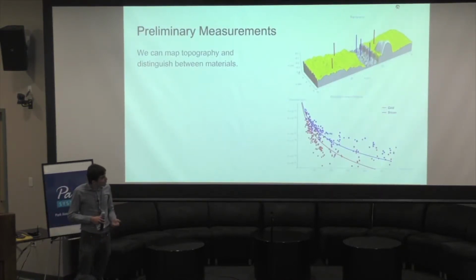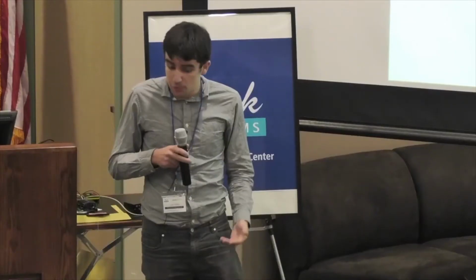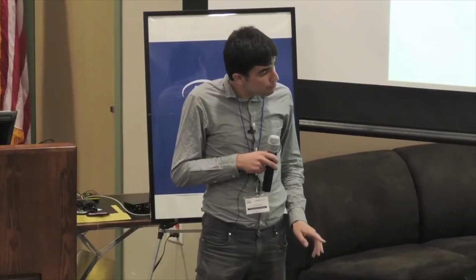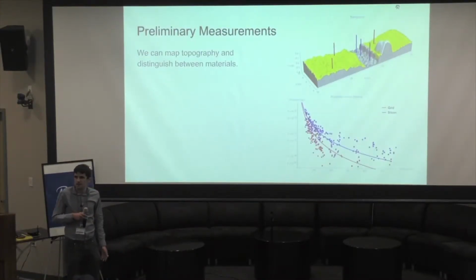So early this summer, we conducted some preliminary measurements with this system on a sample which consists of evaporated gold on silicon with trench geometry. With a more primitive version of the measurement protocol, we were able to get reasonably good topographic data and also material contrast between the gold and silicon, as we'd expect from prior work. The gold exhibited lower dissipation than the silicon did.